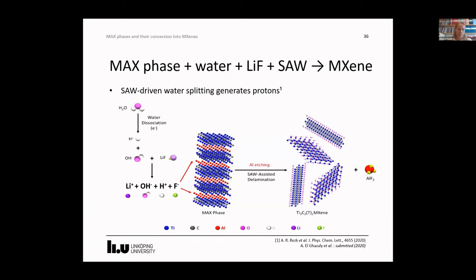And in line with traditional MXene etching, this etches away the aluminium in the MAX phase, and the mechanical vibrations from the surface acoustic waves facilitate the delamination into single flakes.